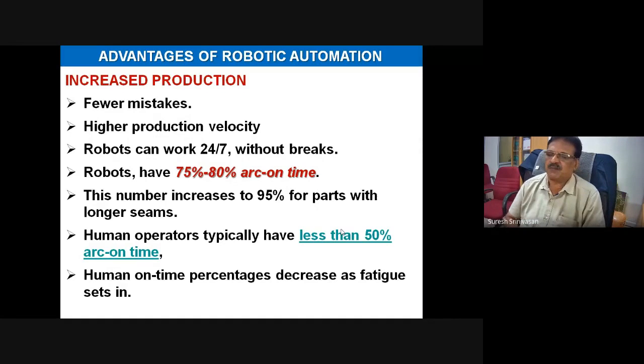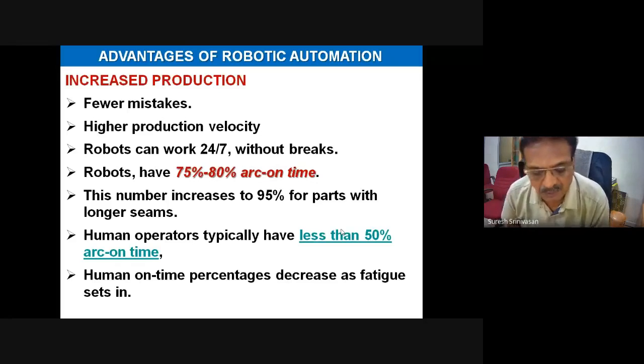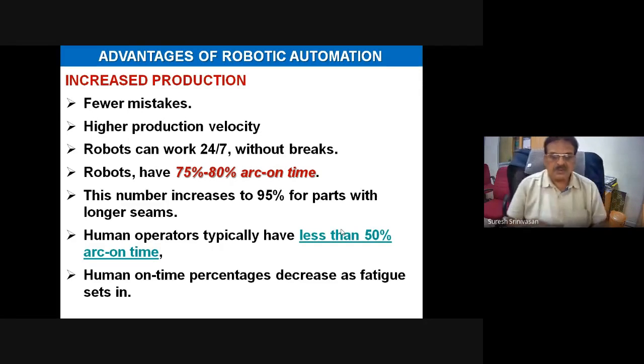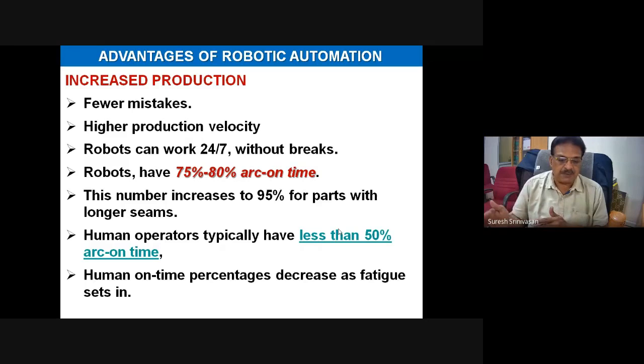So we all aim at going from the 40% level in manual welding to 50 to 60% in SPMs and semi-automatic welding operations. In robotic automation, we can jump to 75 to 80%. So a 40% to 80% jump is what we achieve in a robotic automation system setup. Whereas if you employ human operators for welding, you will have less than 50% arc time. So productivity is achieved by simply one thing, increasing the arc on time from 40% to 80%. So this is the crux of the issue in automation.